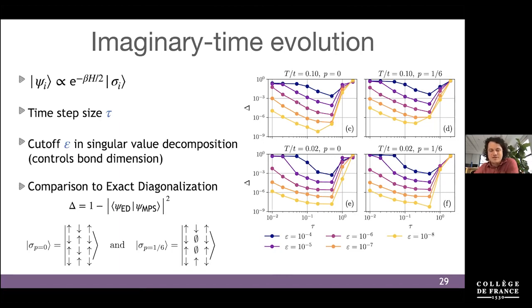And I think this is really nice. On the left-hand side, we always are at half filling, time evolving this state. On the right-hand side, we are time evolving a hole-doped state with two holes. The upper panels are at temperature 0.1 and the lower panels are at temperature 0.02. What is plotted on the x-axis is the time step size, tau, on a log scale. We did it over a range of sizes for this tau.